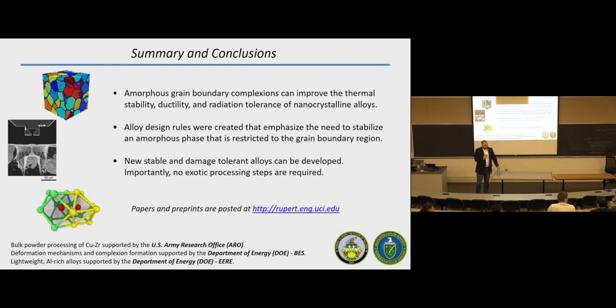So I have a quick question about the thickness of the amorphous layer. Have you, for example, with the copper zirconium, if you add more zirconium, will the thickness get thicker? There definitely will be a composition effect here. We haven't studied that yet because we've been doing it in these random polycrystals in these ball mill samples. The reason is, when you do that, you end up getting a lot of different types of grain boundaries with different local compositions. We are just starting a project where we're going to study this and also the effect of adding the higher complexities.